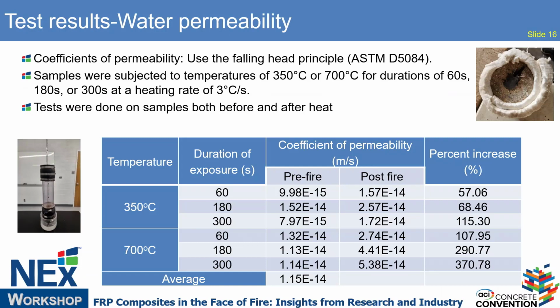So this is the water permeability tester, and because the water penetration test is very sensitive to the concrete composition, in order to reduce the uncertainty, we tried to test the water penetration for one sample before the fire and after the fire. So instead of using samples collected directly after the vehicle fire test, before the fire we collected a couple of samples and measured their water permeability, and then we exposed those samples to a relatively high temperature, and we considered